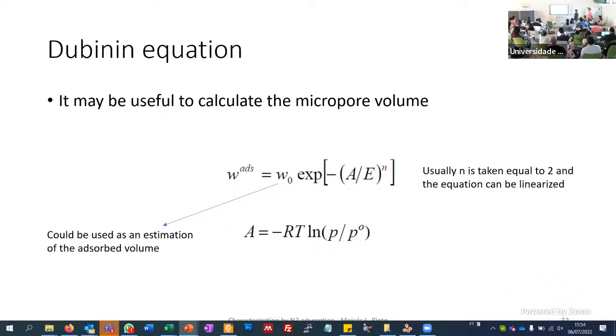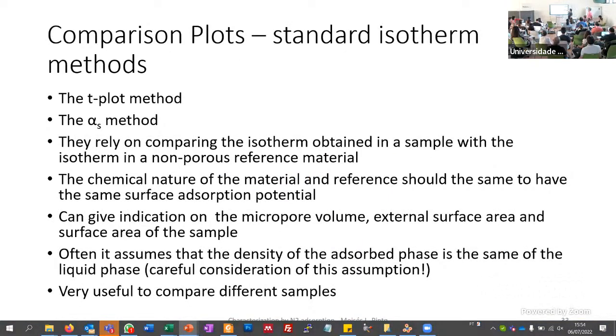We are going to jump to other types of strategy, which are the comparison plots. So we have the t-plot method and the alpha-S method. They rely on comparing the isotherm that we have measured in the actual sample with some standard isotherms, either taken from more theoretical isotherms or even from other real isotherms of non-porous solids. So the standard isotherm is in a non-porous reference material.